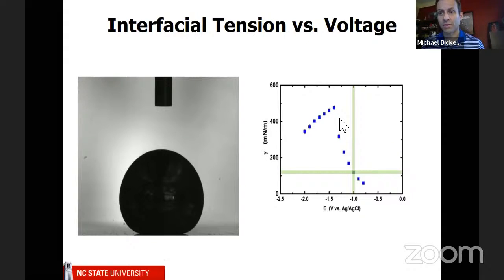We've created pretty stable suspensions, and other people have too. The other thing that's been a little bit problematic is that if you make these things in water, they will react and form that gallium oxide, which I mentioned. So we've created a coating, which I didn't show, that helps stabilize those particles for weeks at a time. And there's been some work from some other groups that have also put polymers on the surface of the metal to help stabilize it. So those are the two things that kind of come to mind.